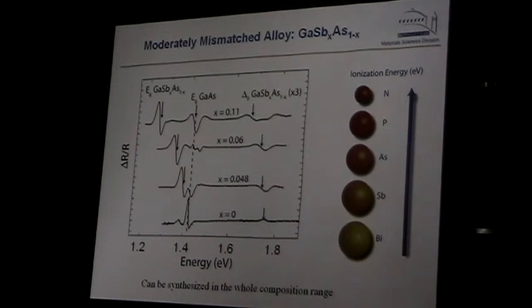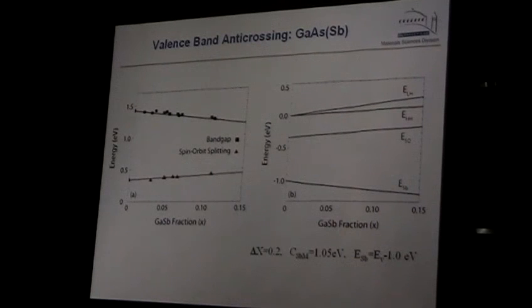So this again suggested that there is some additional anti-crossing, and in fact, the gap here goes quite rapidly. For 10% of antimony, you see the band gap already went down. If you would extrapolate it to gallium antimonide, it probably would go to much, much smaller than gallium antimonide. So there is an initial very rapid change in the band gap. But it's not as dramatic, I have to admit. This is what we sometimes call moderately mismatched alloys, because the effects are much, much smaller.